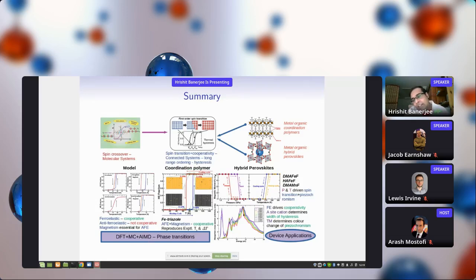In hybrid perovskites, we also have a very interesting phenomenon happening where the A site cation determines the width of hysteresis or the cooperativity due to the hydrogen bonding, the differential nature of hydrogen bonding of the A site cations, and the transition metal determines the color change of piezochromism. And there are a wide range of device applications which are possible with these materials.